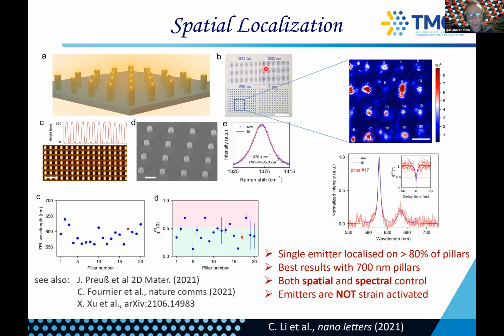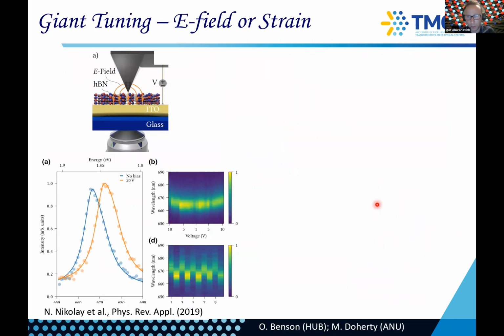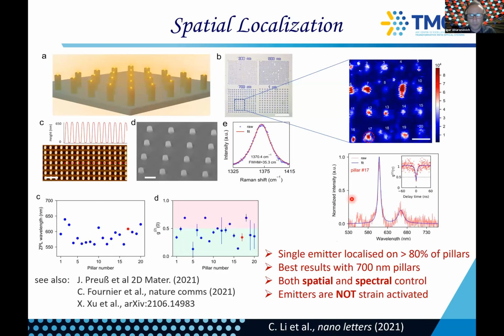And so we made different pillars. I won't bore you with details, but somehow 700 nanometers works the best. And you can see here just a confocal microscope of an array of 5 by 5. And so this is an example of pillar number 17. It has a single photon source, very similar spectrum to the previous work here, grown on copper. And you can actually see remarkably that all the pillars basically show you this spread of around 600 nanometers as expected, and most of them are actually singles.